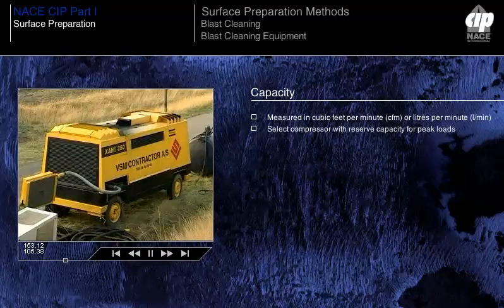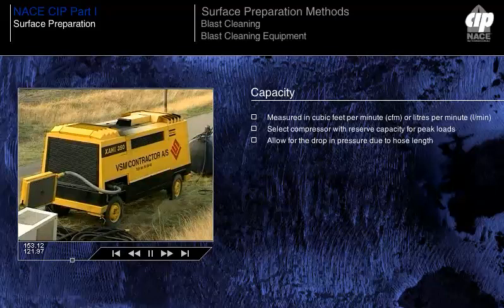It is estimated that with one 3/8 inch, 9.5 millimeter nozzle operating, there will be a 5 pound, 35 kPa drop in pressure for each 50 feet, 15 meters of hose in use. This pressure drop will be compounded according to the number of operating nozzles, the nozzle sizes, and the lengths of hose being used.